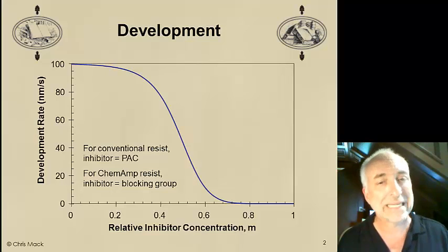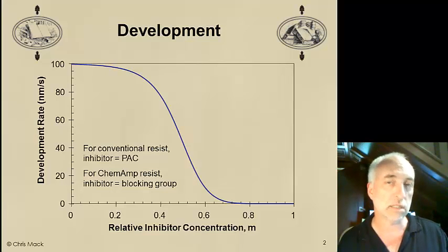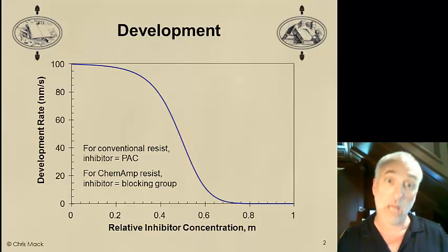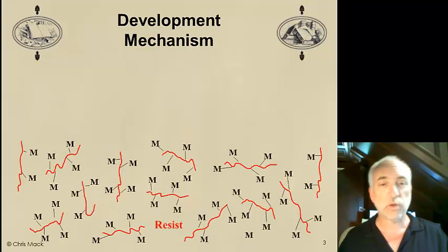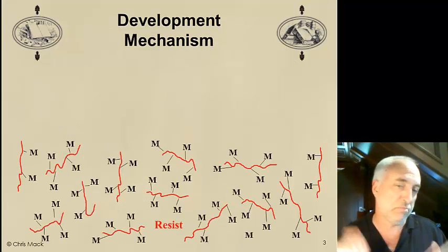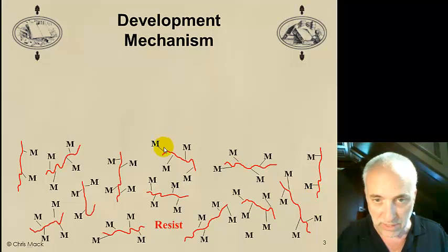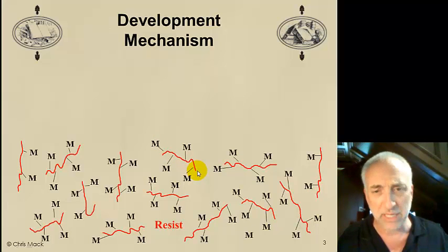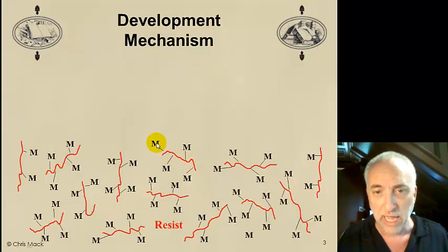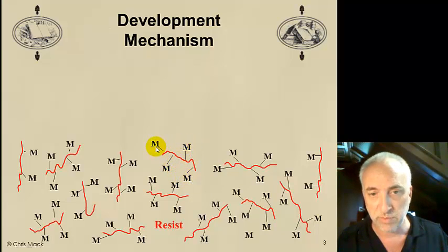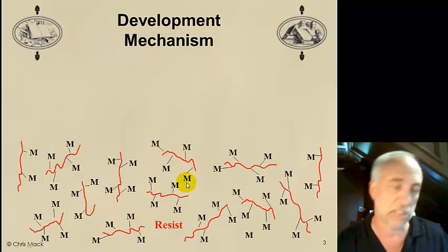How do we get a highly nonlinear resist? I'll explain. Suppose I have a photoresist that I'll make in a cartoon way look something like this. The red squiggly lines here represent the polymer. I'll think of a chemically amplified resist as my example. And then on this polymer I have certain blocked sites given by these M. In this example I show one polymer with 4 blocked sites.